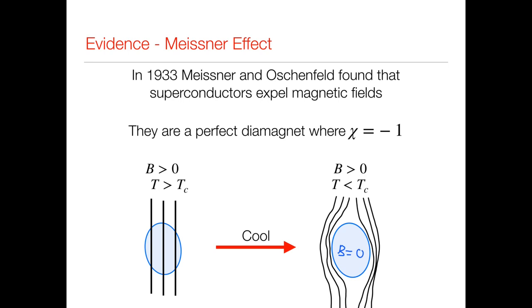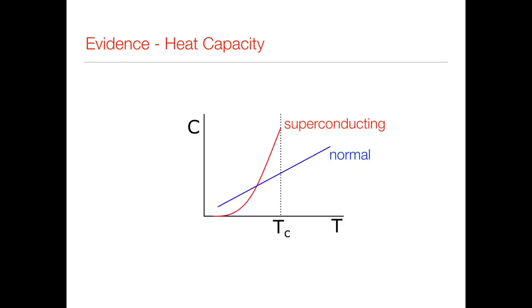So what other evidence do we have? There's evidence from the heat capacity. In the blue line here, I'm showing how the heat capacity varies with temperature for a normal material. It should just go linearly down to 0. What actually happens in the superconducting state is when we reach Tc, the heat capacity jumps up. It's discontinuous, it jumps up, but it rapidly drops down very close to 0. Looking at it the other way, this actually looks like an exponential function, and then a transition back down to the normal. So for the heat capacity, the superconducting state is acting very differently to the normal state.